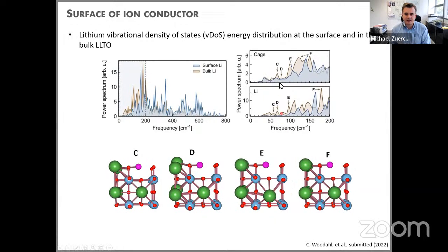So these are the actual lattice modes for C, D, E, and F. Those are the ones that are strongly suppressed in the case of the surface. What we then found out is that this gives rise to a reduced lithium hopping. From the X-ray measurement, we got the input to say there is something different here, which pertains to shifts commensurate with a shift in the phonon spectrum. In turn, this allows us to estimate reduced lithium ion hopping rates at the surface.